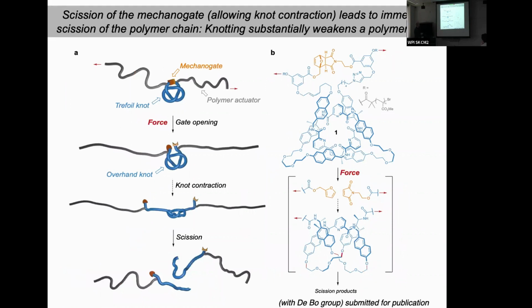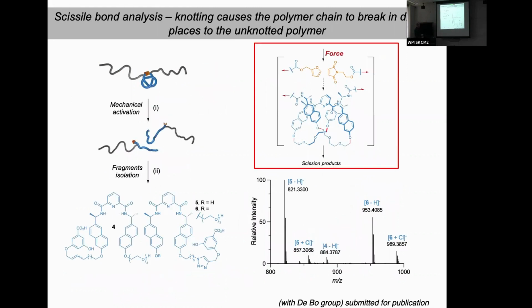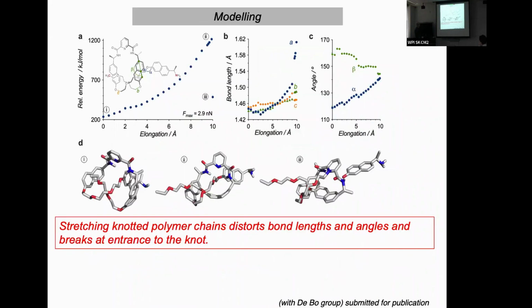So more than that, this is actually what's happening here, and we can actually see the fragments of where the knot breaks. And by looking at the products that we isolate, we can see that the knot breaks at these points here, which are actually the entry points to the knot, just as theory predicted 25 years ago.